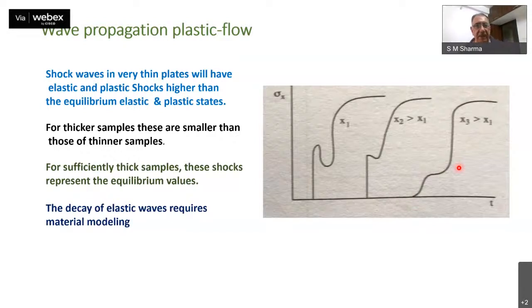So shock waves in a very thin plate will have elastic and plastic shocks higher than the equilibrium elastic and plastic states. For thicker samples, these are smaller than those of thinner samples. And for sufficiently thick samples, these shocks represent the equilibrium value. And incidentally, if you want to study this decay as a function of time, one requires material modeling of how that instantaneous metastable state evolves. So one has to see what exactly happens under the plastic deformation and so on. So there are models, we will not talk about it.